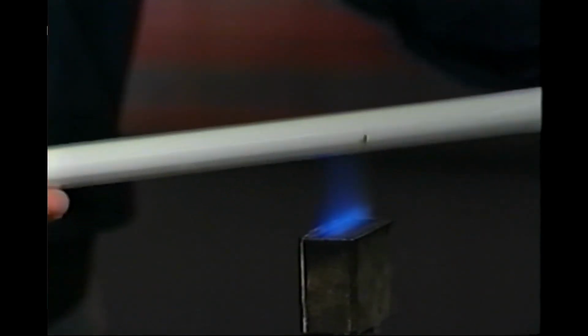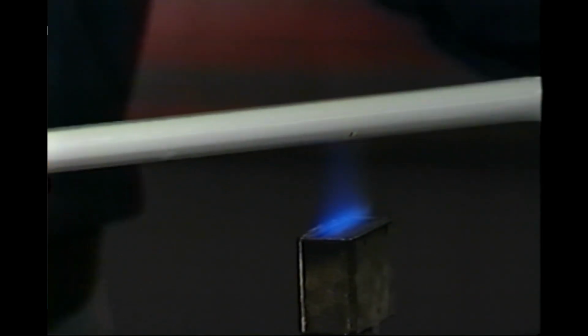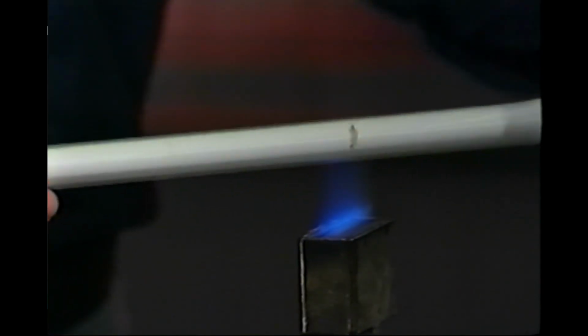The mix of gas and air can vary to some degree, but the width of flame must be sufficient to melt the correct area of glass for any given bend. For example, the width of glass to be melted for a right angle bend should be equivalent to 2 diameters of the tube being bent.